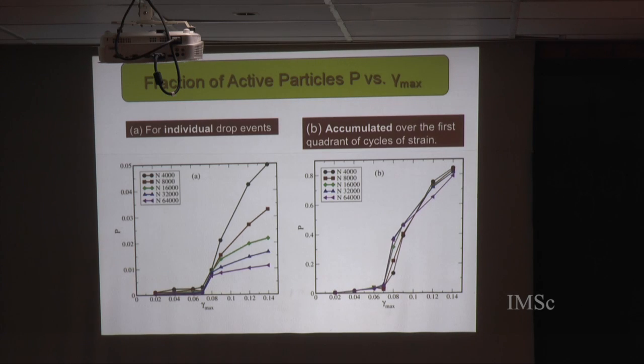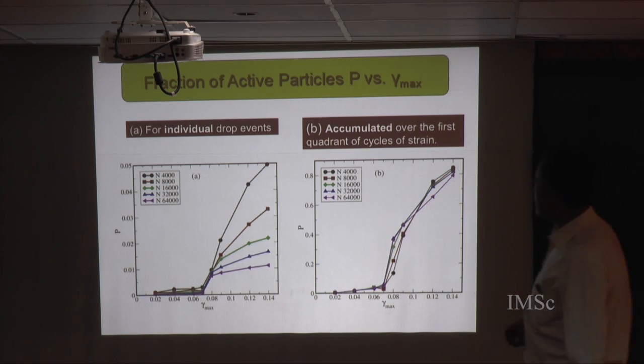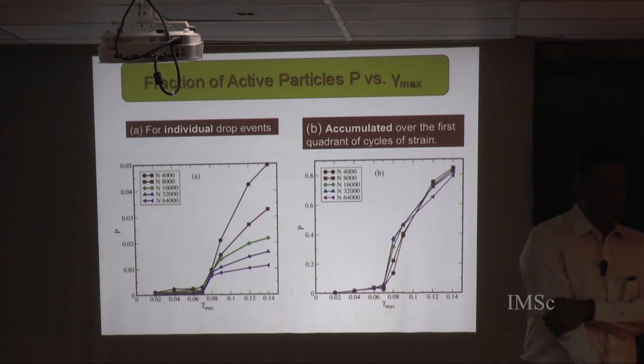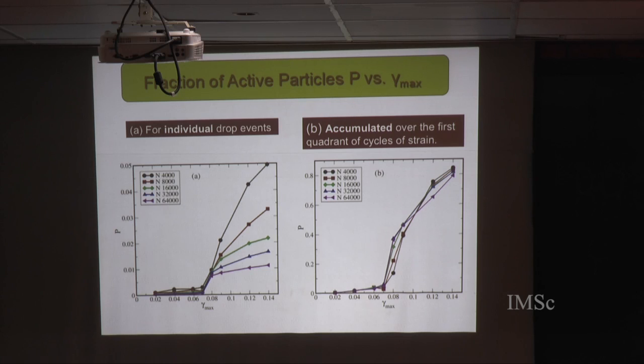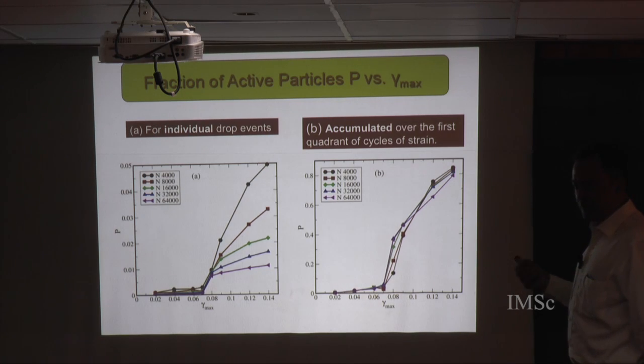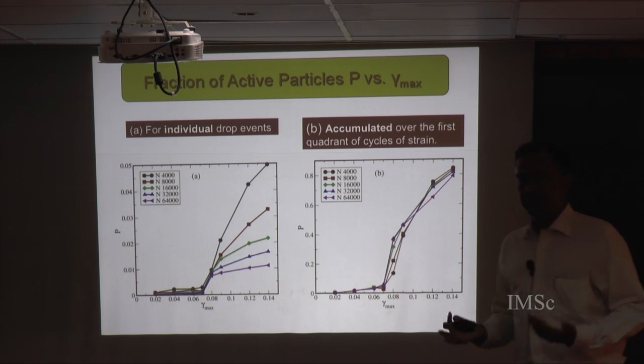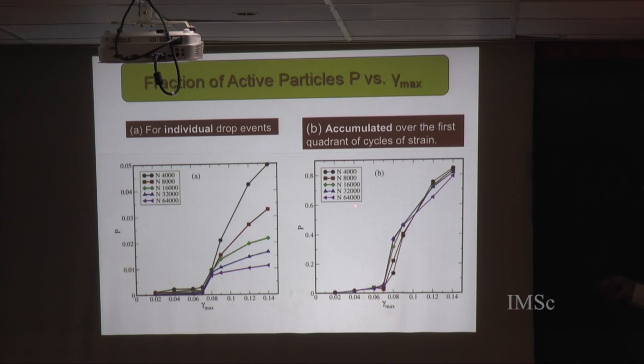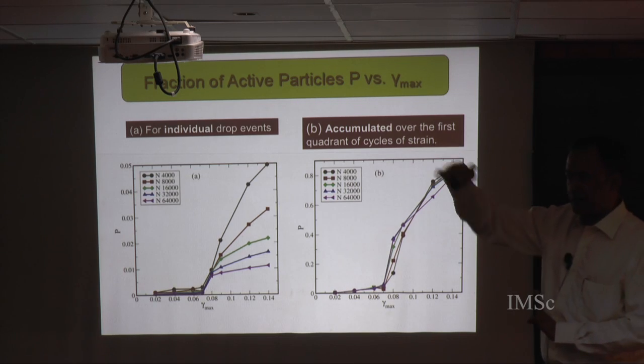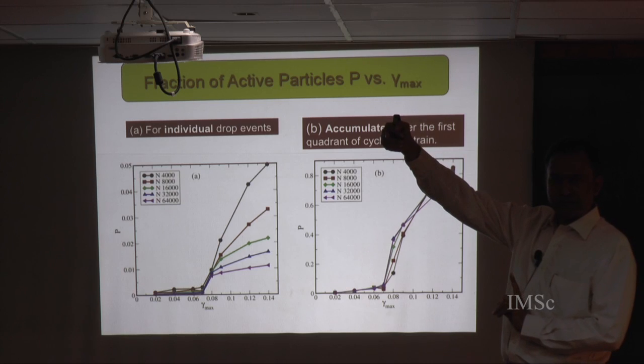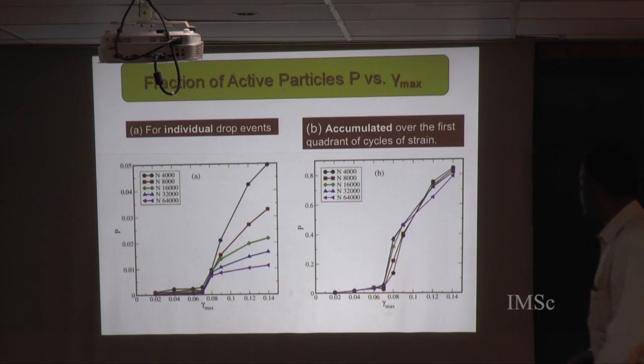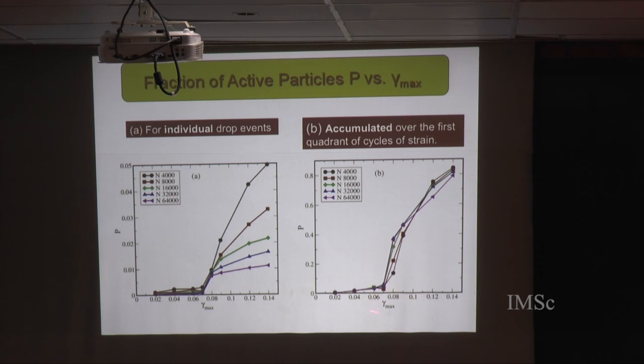So finally, we look at the percolation characteristics, and we've done it in a couple of different ways: either looking at individual drop events and asking what is their percolation behavior, or looking at an accumulation of particles that participate in a plastic event through a quarter of a cycle and asking what happens to their percolation. The quick statement is that there is a percolation transition that takes place at the yielding transition.